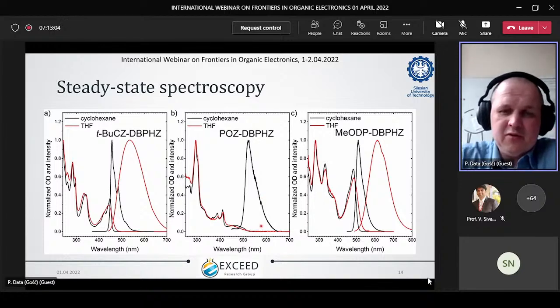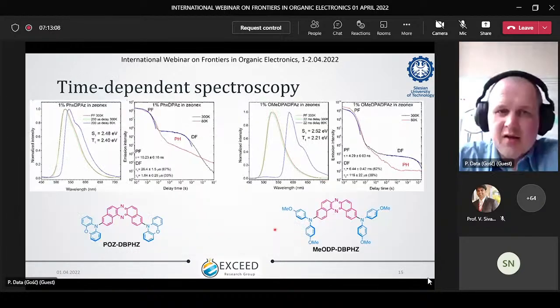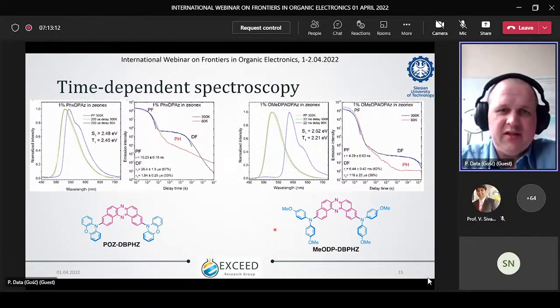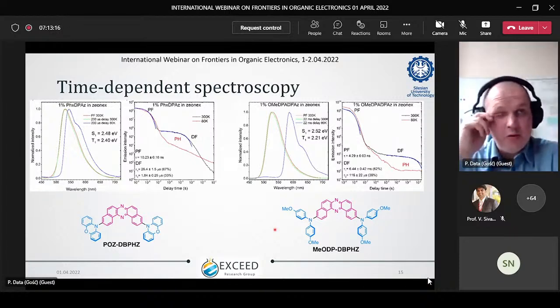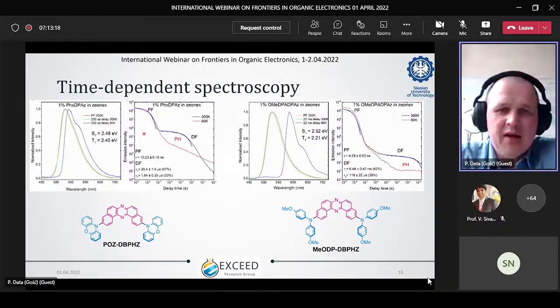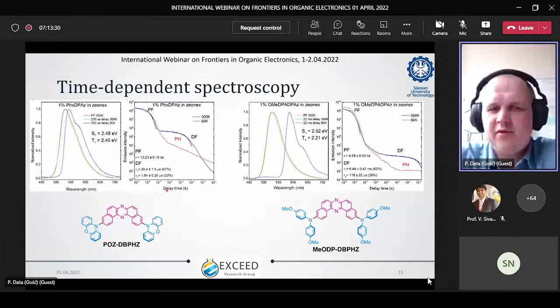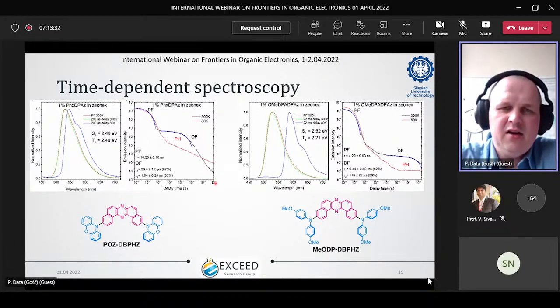But if it disappeared, that means there is a chance that your emission is quite strong. Then we are going to the more sophisticated analysis, time-dependent spectroscopy, time-dependent emission, where we are using our laser setup and we are exciting our molecule in the nanosecond times, and then we are gathering the emission spectra at different times from the nanoseconds up to second time region.